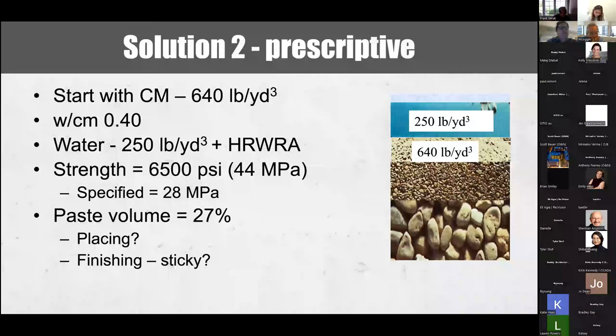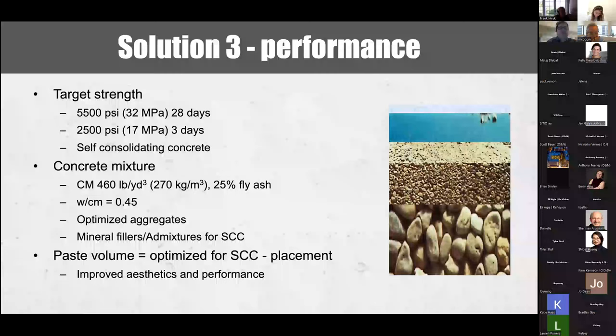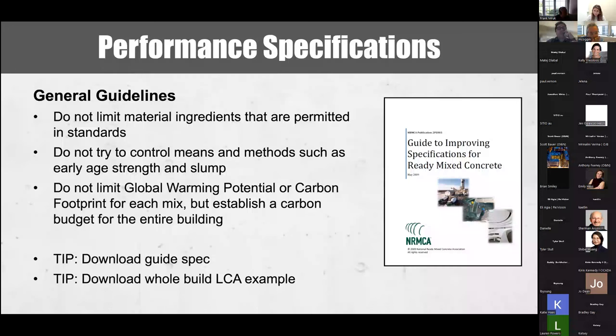In a performance-based mixture, the producer can develop optimized mixture approaches to achieve the early age strength required by the contractor and the later age strength required by the design. An option would be to use a self-consolidating concrete to facilitate placement. This mixture has the lowest paste volume that brings other benefits with it. These are the guides to performance specifications for ready mix concrete that NRMCA produces.